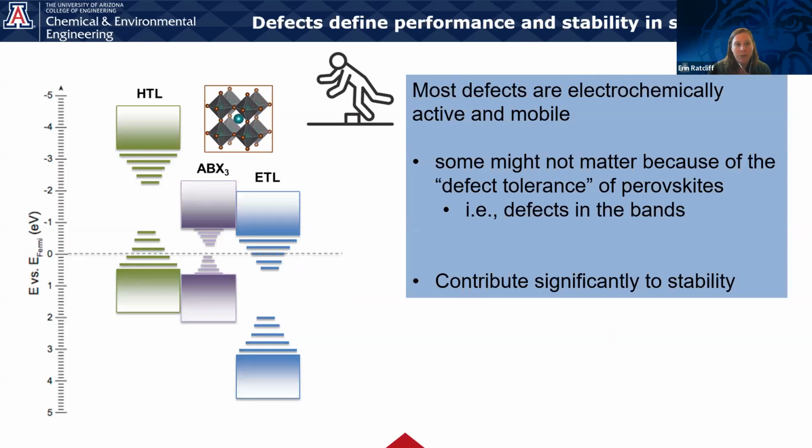What we'd like to do, for example, is the light comes in, you create the holes and the electrons. You'd like to pull the holes out of the perovskite through the HTL into the ITO. What you would want to prevent is the injection of holes from the ITO through the HTL into the perovskite. So you've already created an asymmetric interface for charge transport. And then you want to ask a question where you use a measurement that thinks about oxidation and reduction on a system where you've designed a preferential highway for charges.